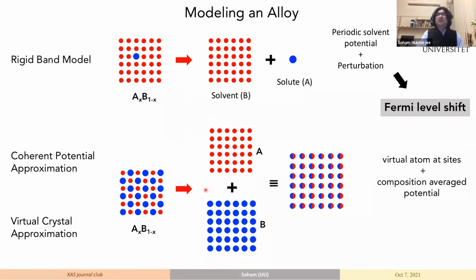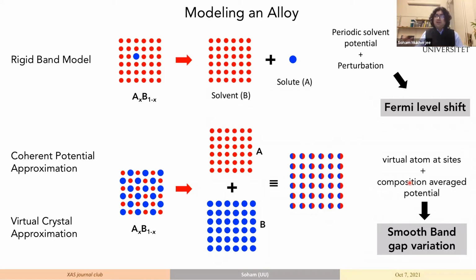And this is how the virtual crystal approximation also came into being, that you assign an average potential of A and B and put that potential at one particular site. So then what you have is basically a composition averaged potential at one particular given site, and all virtual atoms are sitting at an ideal lattice site. So the basic difference from the rigid band model to the virtual crystal is that now you have a smooth band gap variation.